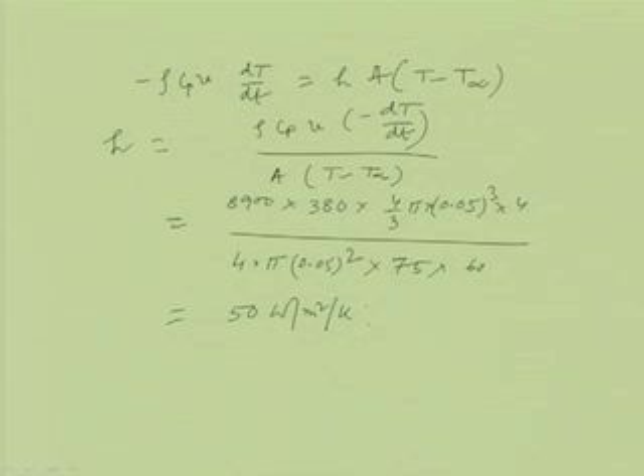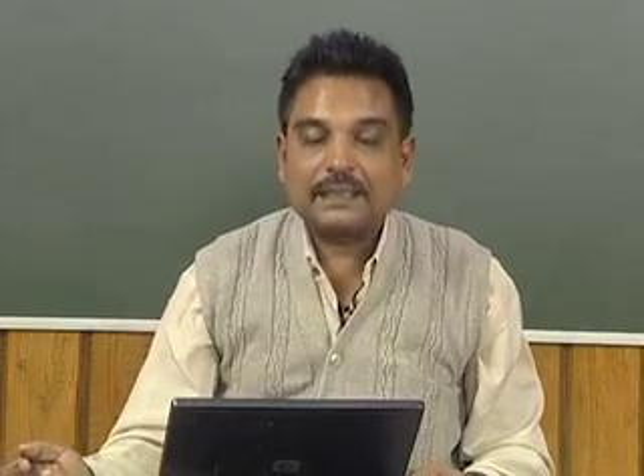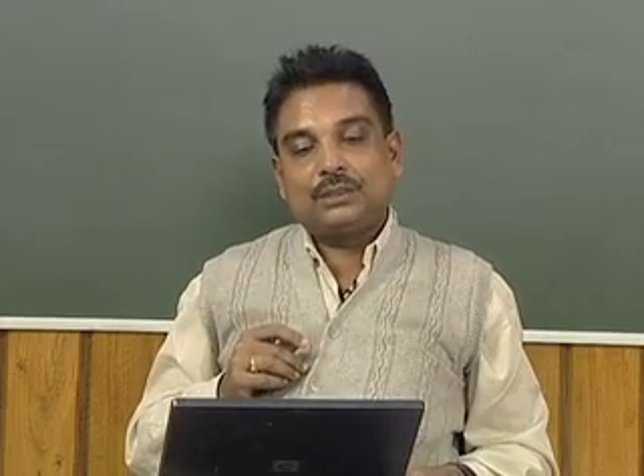So this h, the convective heat transfer coefficient between the copper ball and the environment, is 50 watt per meter square per Kelvin. So we can calculate, even by doing some experiment with proper measuring of the temperatures, the convective heat transfer coefficient using the lumped parameter model.